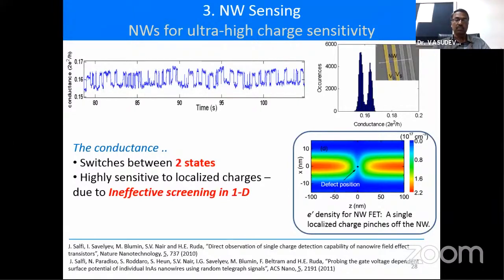And then you'll get a Poisson distribution that is as shown on the right, showing two well-defined discrete states. And the electron transition from one state to the other is what we're actually looking at then. And indeed, because of the sensitivity to local charges, that transition from one to the other can actually be used to pinch off or shut down the transistor. And much of it is due to weak or ineffective screening that I spoke about earlier.